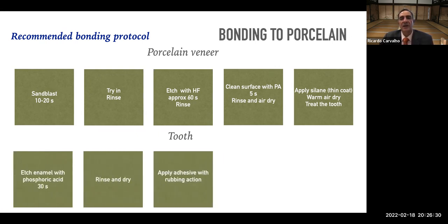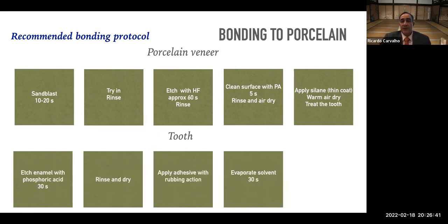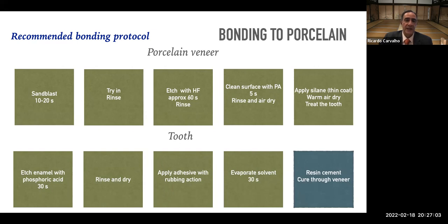If there is enamel, you etch the enamel with phosphoric acid for 30 seconds, you rinse and dry, you apply your adhesive. Usually there is a recommendation with a rubbing action to, again, favor the solvent evaporation, which is really important. Solvents are present in most of our products, and they're there for a reason, just to make the product usable in terms of viscosity, application. But the solvents, they do not help in anything at all. They need to be evaporated before you cure.